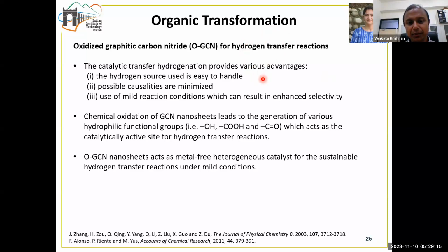So what we have done is we have prepared a catalyst, again a graphitic carbon nitride based catalyst, by a chemical oxidation method, and this leads to a lot of functionalization of these graphitic carbon nitride nanosheets.